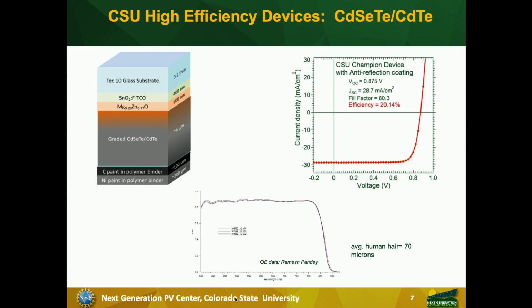So this is our claim to fame, that this is the structure we have finally developed that is our highest performing device structure. We get a glass coated with fluorinated tin oxide. This is what is called low-E glass. It's a commercial product and sells for about $10 a meter square. It's quite low cost. And then we invented this material, magnesium zinc oxide, that is put on top of it. And some of the leading companies are beginning to use this now.